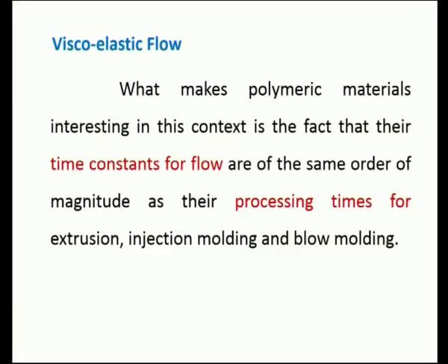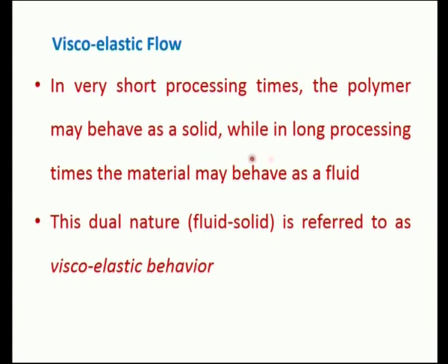Next, the viscoelastic flow. What makes polymeric material interesting in this context is that their time constants for flow are of the same order of magnitude as their processing times, irrespective of the process: extrusion molding, injection molding, or blow molding. Or in other words, in very short processing times, the polymer may behave as a solid, while in long processing times the material may behave as a fluid. It goes to both extremes, from highly viscous to highly elastic. This dual nature of fluid to solid is referred to as viscoelastic behavior.